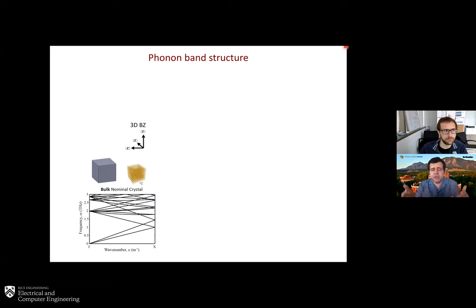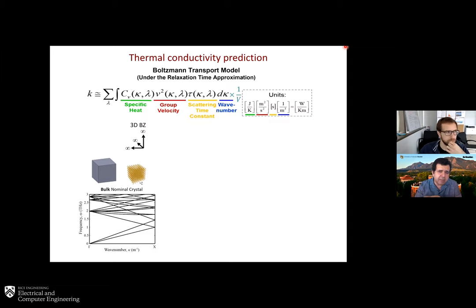And then, obviously, we're interested in the thermal conductivity. So there are different ways to do that. And I'm going to take a minute to describe one of the techniques that I think serves a very useful purpose, in that it actually provides us with some insights. So it's not a black box technique like some of the other approaches where we just analyze thermal transport using molecular dynamics simulations and so on. Here, this is an analytical approach that allows us to predict the thermal conductivity using the Boltzmann transport model, specifically under the relaxation time approximation.